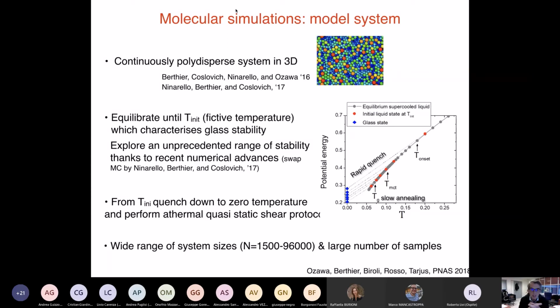Now, in real simulation, the difficulty is that it's actually very difficult to prepare an amorphous system which is very well annealed. The reason is that, to be very well annealed, you have to equilibrate on a very large time scale. And this is what makes the problem very difficult. Now, there has been a breakthrough in recent years on the ability to prepare a very well annealed amorphous system.